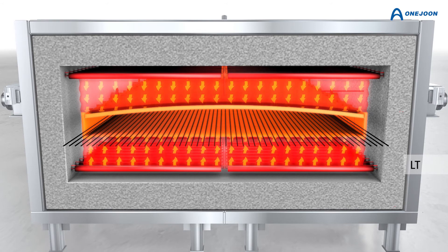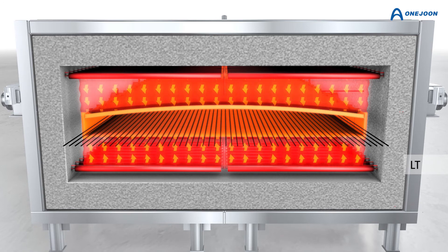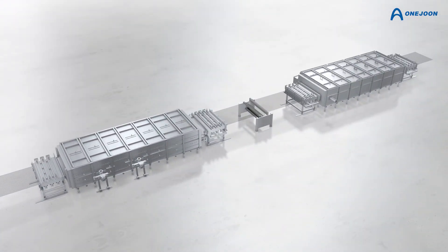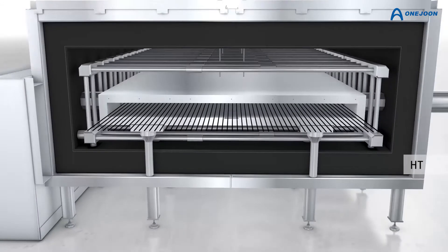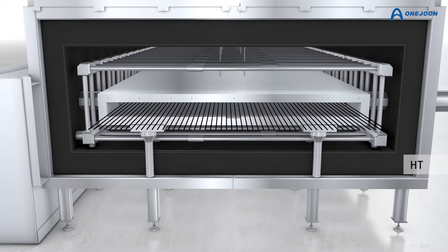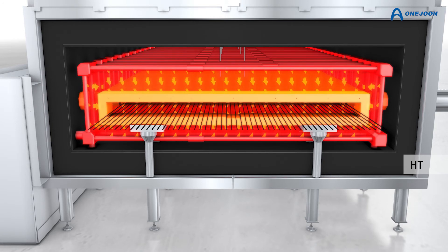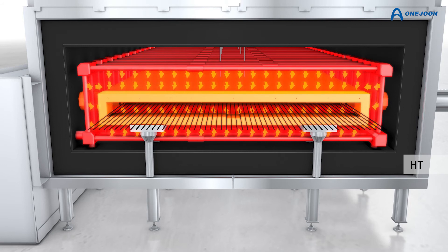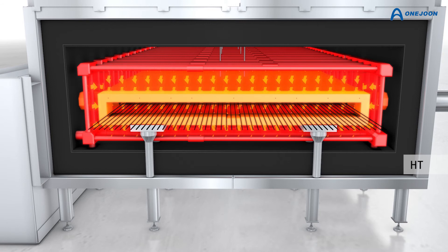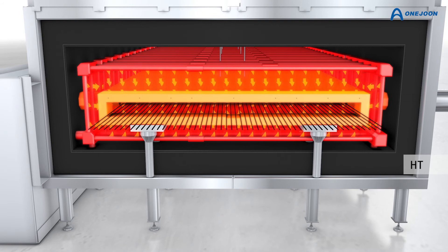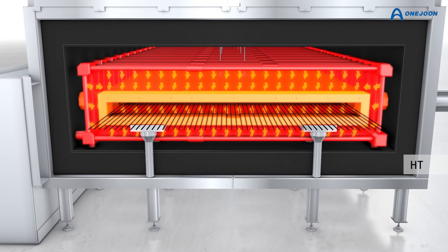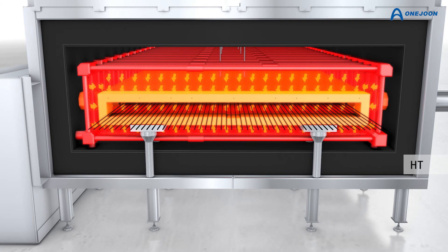Also offered by OneJoon is the proven gas-fired LT furnace technology to utilize the cost savings when using natural gas. The high-temperature furnaces typically see temperatures up to 1,800 degrees Celsius. A graphite muffle construction is utilized to manage these high temperatures. Our proprietary heating system frames the graphite muffle with a cage of heating elements, ensuring best-in-class temperature uniformity within the furnace chamber and over the entire fiber band. This custom design significantly reduces the number of penetrations in the oven housing by 75%, avoids additional heat loss, lowers the overall energy consumption used for cooling, and reduces the risk of oxygen infiltration significantly.